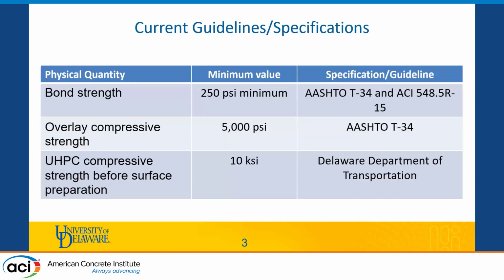So what we have in terms of current guidelines is, one, a minimum bond strength of 250 PSI is recommended by AASHTO T-34 and ACI 548 when you have overlays on normal concrete. We also have a recommendation of the overlay having a minimum compressive strength of 5 KSI. And Delaware Department of Transportation requires that ultra performance concrete should have at least 10 KSI before you prepare the surface and apply your overlay material.